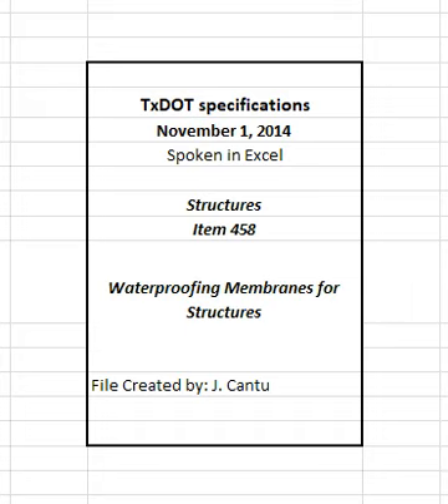Use asphalt for mopping below ground as defined in DMS 6300, waterproofing, when asphalt waterproofing is shown as a protection for back of abutments, retaining walls, or footings. Use asphalt for mopping above ground as defined in DMS 6300, waterproofing, for waterproofing on bridge decks. 3.2 Type 1. Do not apply waterproofing in wet weather or when the ambient temperature is below 50 degrees Fahrenheit. Ensure the rubber membrane is free from punctures, pockets, or folds.